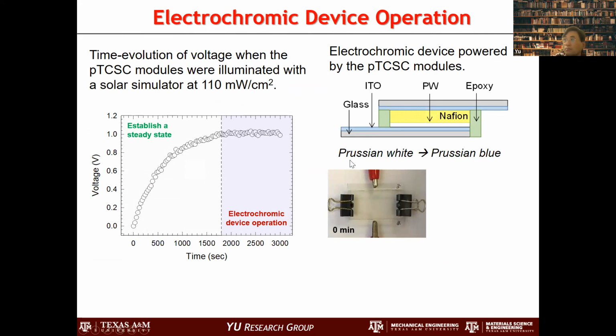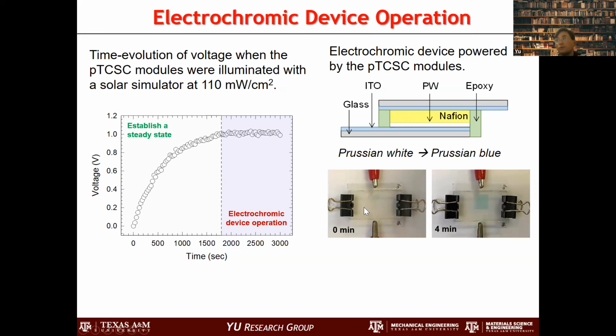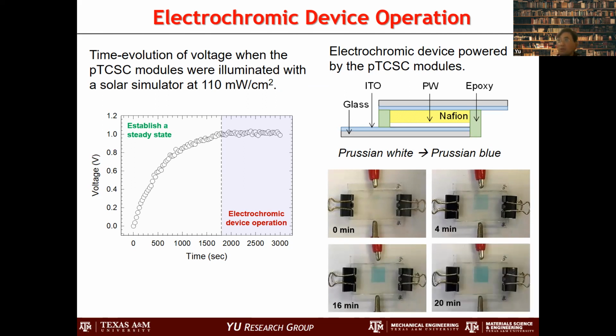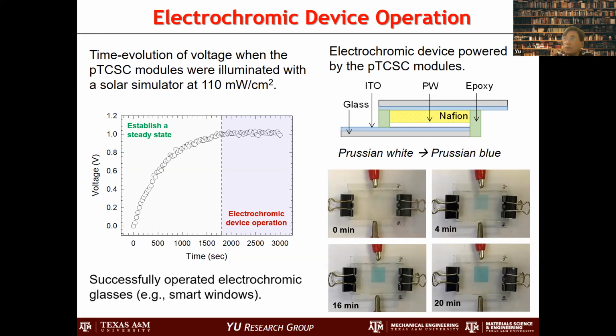So this is what we call Prussian white, and Prussian white becomes Prussian blue when we supply electrons. Initially this is transparent, and then after we apply a temperature difference and supply electrons, it becomes more bluish, darker and darker. This kind of electrochromic device is actually used for smart windows, so that we can shut off sunlight, for example, like this. And we actually demonstrated that this could be used in practice. That's what we have done.